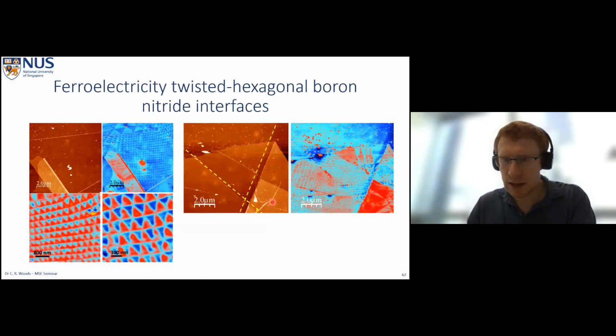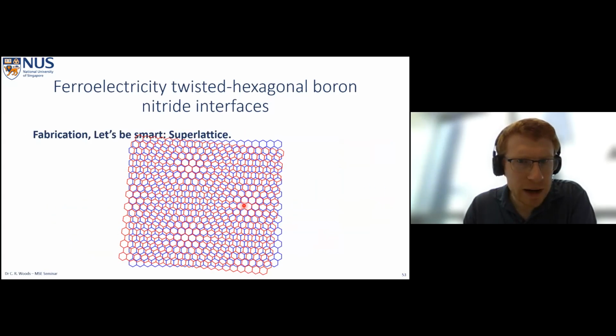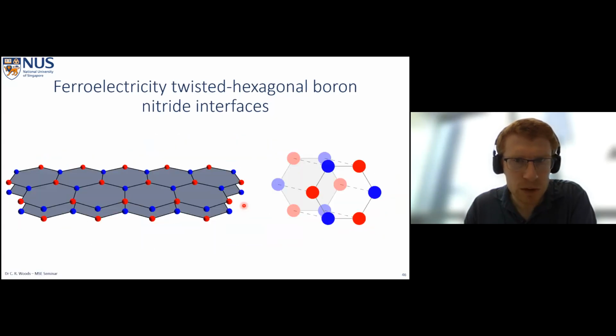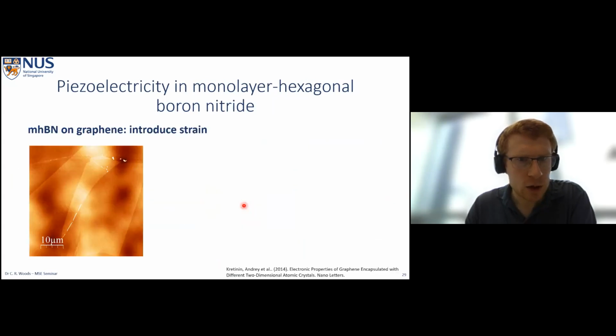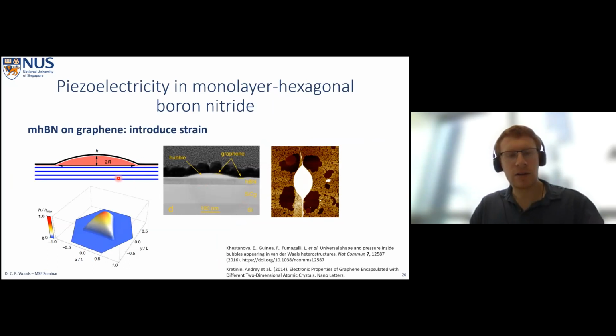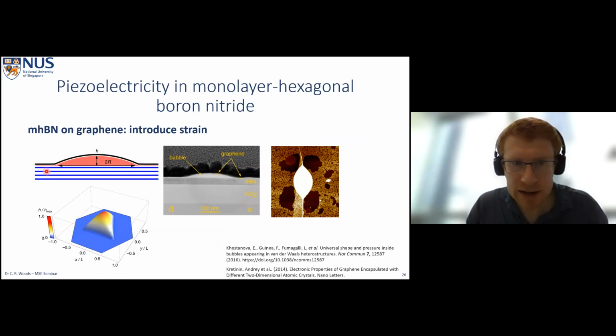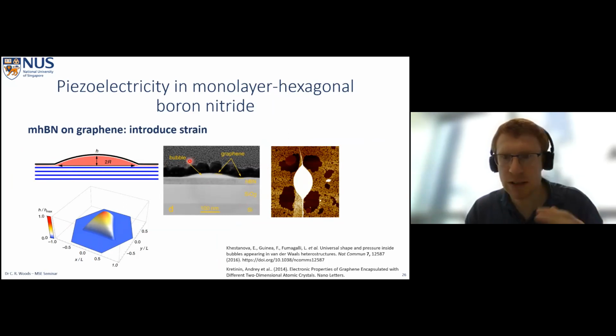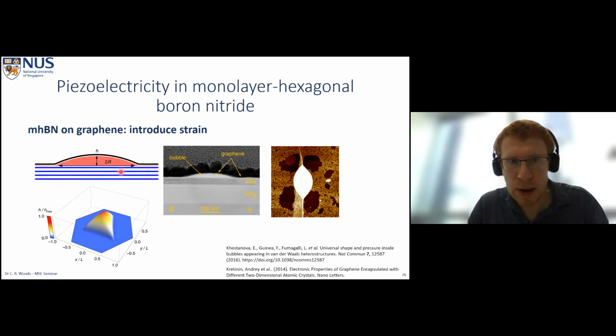Okay, so I think the answer to that question is really, let's go back to the theoretical look at what is in these bubbles. So we have to go quite a long way back. Okay, here. And so what we can say is that just due to the fabrication process, something like this will happen. So we would expect that if we have just a monolayer boron nitride as our substrate, and then we put graphene on top, the bubble would more affect the layer you put down second, because your monolayer boron nitride is going to be on a substrate, silicon dioxide or something like that. So its ability to bend downwards is going to be limited by the fact that it's already on a substrate.